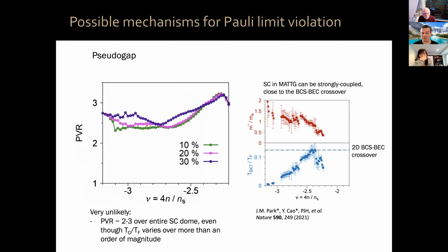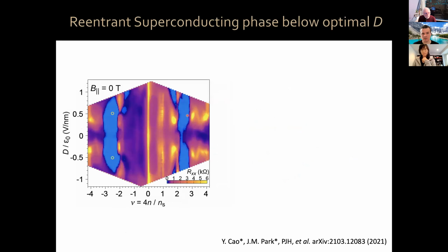But if we measure the Pauli violation ratio as a function of filling factor, we see that it does not depend very strongly, and it's always above 2, in the entire superconducting dome. Okay, even in regions where the coupling strength is much, much weaker, and we don't expect to have big energy preformed pairs. So, moreover, none of the mechanisms that I have just told you about can explain this reentrant superconductivity, which we observed at higher magnetic fields.